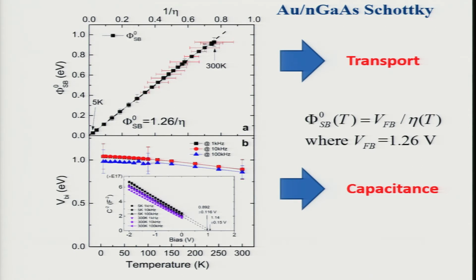So this is low voltage measurements giving us the flat band voltage, which you measure directly with capacitance, which is in reverse bias. And from these nice linear extrapolations, we get a good agreement with the intercept here with the calculated flat band voltage of 1.26 from the forward bias characteristics. So the whole point of this is that you can use both forward bias and reverse bias. One's a capacitance measurement, the other is a transport measurement, and you can check what the flat band voltage is. And now we get to some physics.